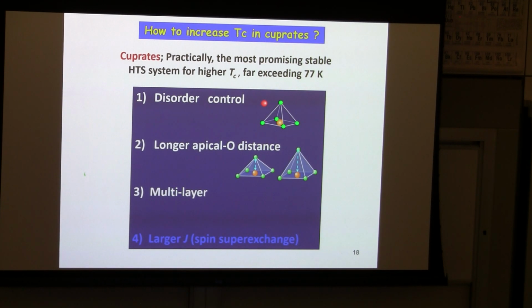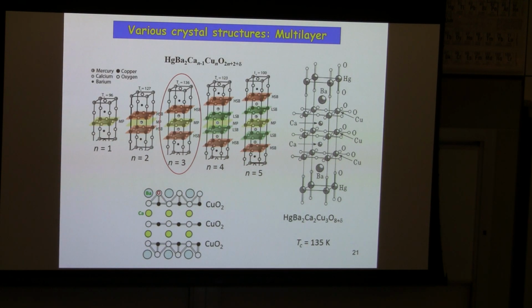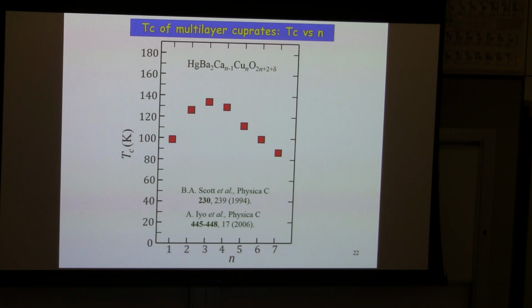And the third one, that is quite effective in enhancing TC, is to make a package of many copper oxygen layers. We call this a multi-layer effect. Okay, this is a typical example of the multi-layers. This is the mercury-based one, which showed the world record TC value for this particular case. This is a package of 3 copper oxygen planes that recorded TC 135K. But there are other packages, 1, 2, 4, 5, even more. And we knew that the TC actually goes up when the number of copper oxygen layers increases: 1 layer, single layer, double layer, 3 layers.